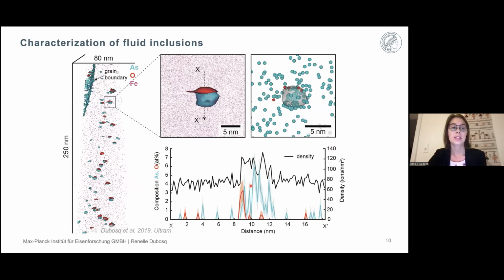And here's the reconstruction. In this reconstruction here on the left side of the slide, the pink dots represent iron atoms or ions, whereas the turquoise isosurfaces represent regions enriched in arsenic, and the red isosurfaces represent regions enriched in oxygen. We noticed throughout this data set that we have these ubiquitous arsenic and oxygen enriched clusters. If we take a closer look at one of these clusters, we notice that they are mostly made up of an arsenic enriched sphere overlain by an oxygen enriched disc-like shape. And if we take a composition profile across one of these features, we notice that these clusters also correlate to high point density features within the data set.